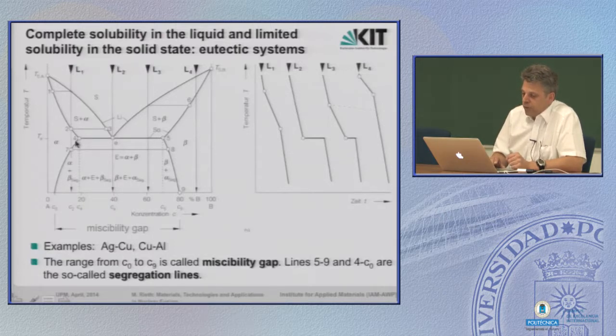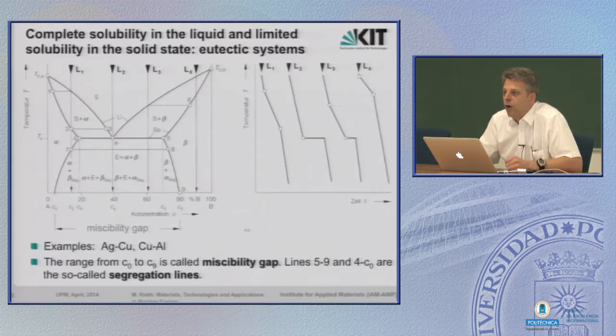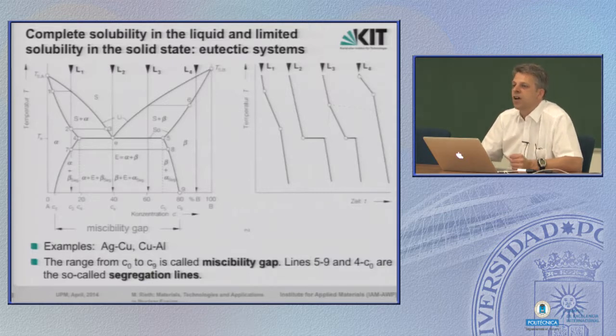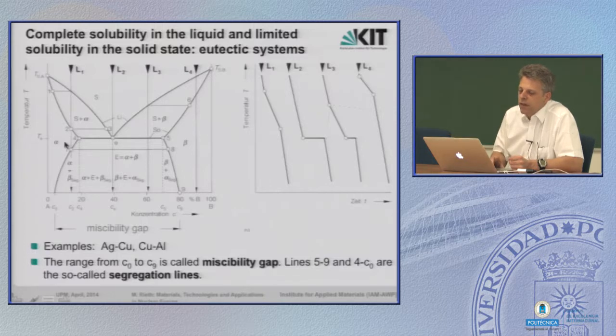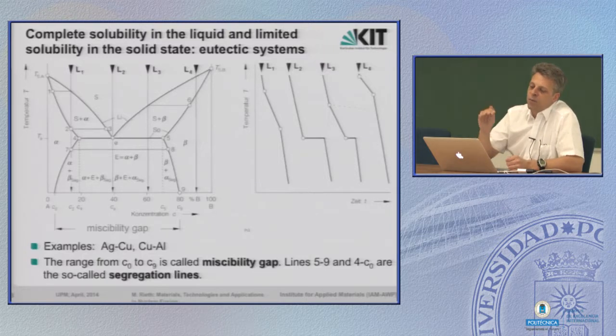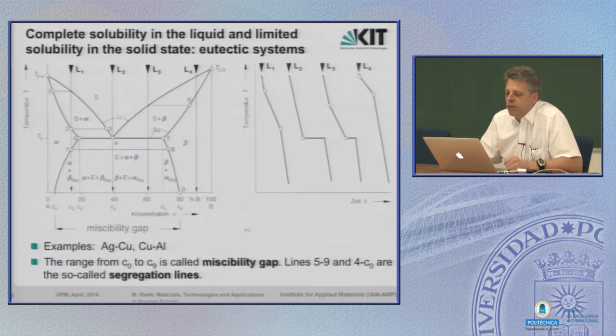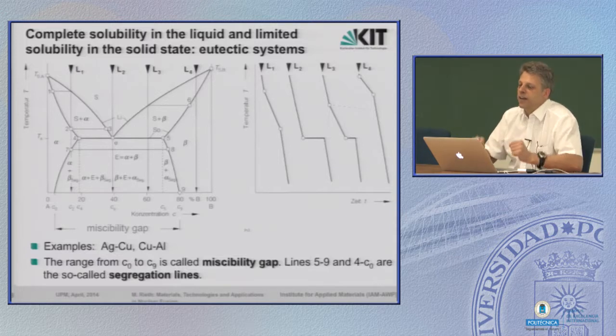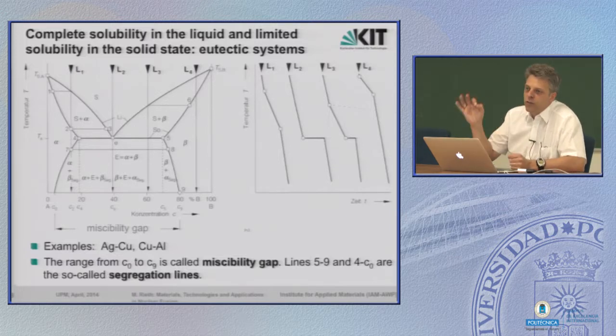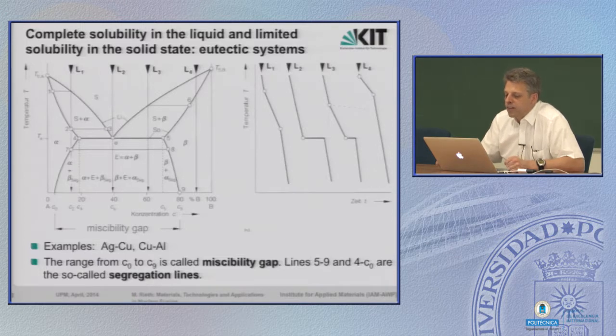And so if we have such a composition, this is the typical case for metals or for alloys that can be precipitation hardened. You bring the whole system into solid solution here in alpha phase, then you quench them down or cool them down rapidly, and by additional thermal treatment, or if you have time to wait, then you wait until the segregation takes place, and this produces precipitates in the material, which brings the hardening.